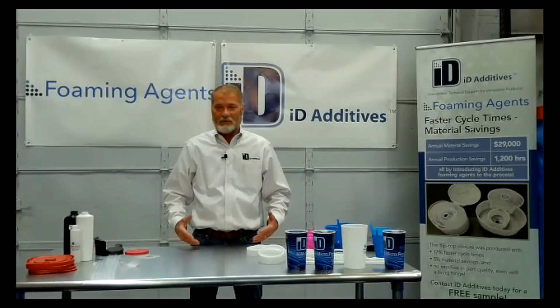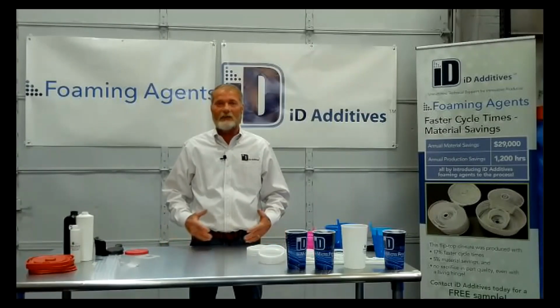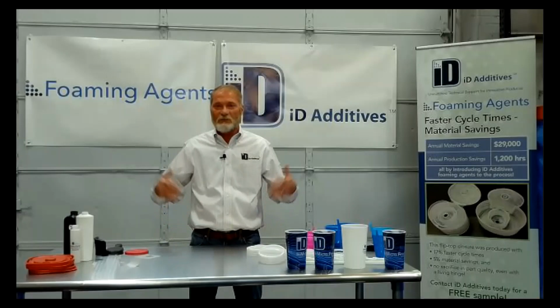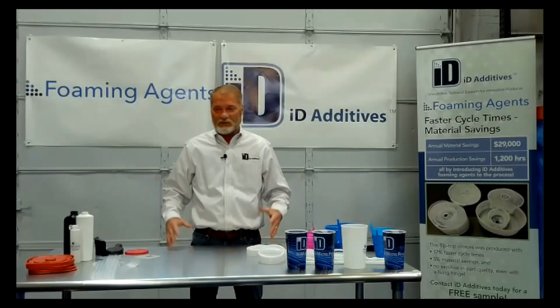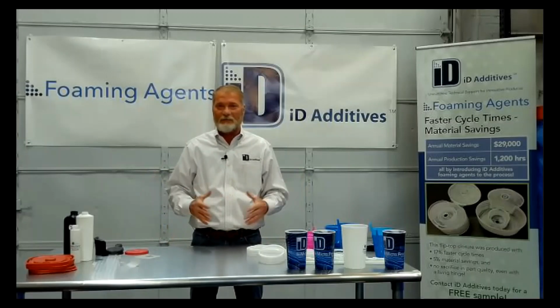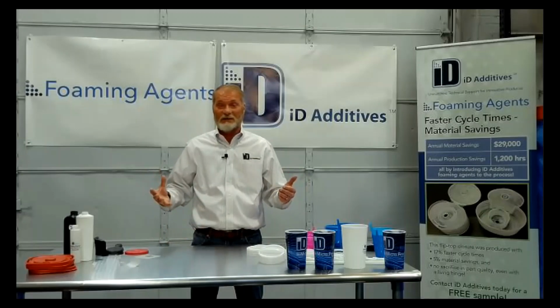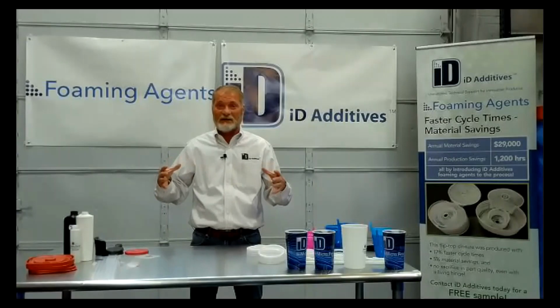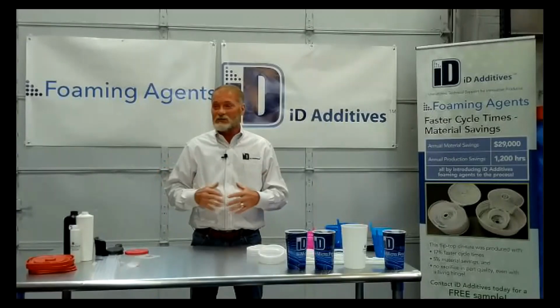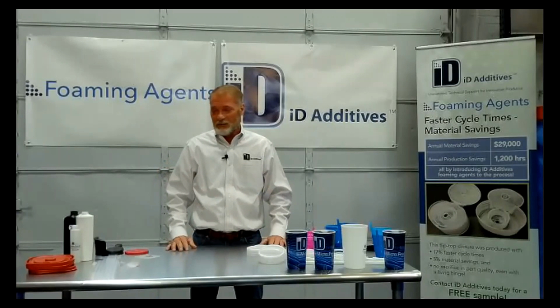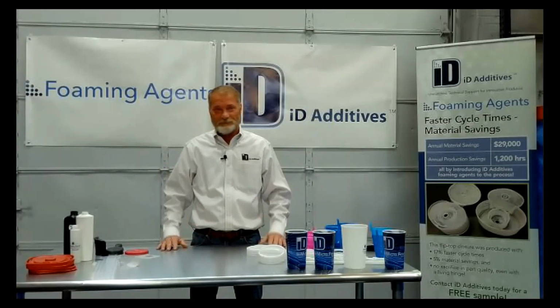If you're dropping 0.5% or 1%, let's say easy math, 1 pound per 100 pounds of resin, you're not going to batch mix that to evenly disperse it. So I always recommend auger feeding it.